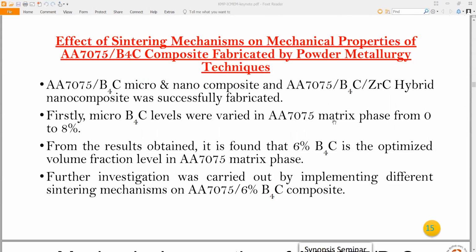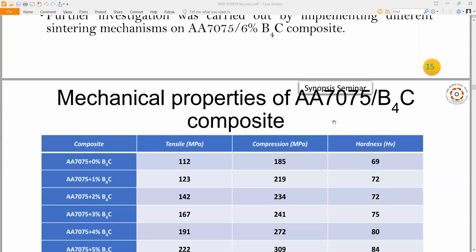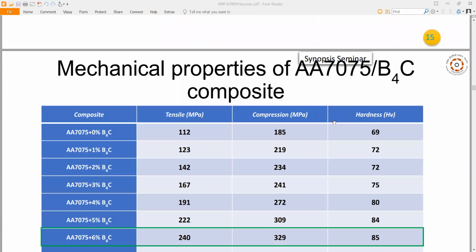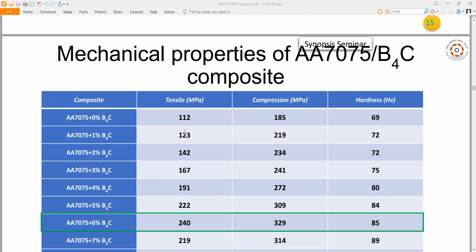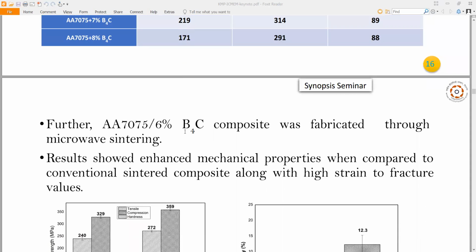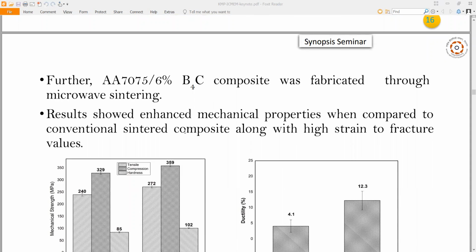From the results obtained, it is found that 6% B4C is the optimized volume fraction level in the A7075 matrix phase. Further investigation was carried out by implementing different sintering mechanisms on the A7075 6% B4C composite. Mechanical properties of the A7075 B4C composite: here we can see the name of the composite, then tensile properties in MPa, compression properties in MPa, and hardness also. So all are given. Further, A7075 6% B4C composite was fabricated through microwave sintering and results showed enhanced mechanical properties compared to the conventionally sintered composite, along with high strain to fracture values.